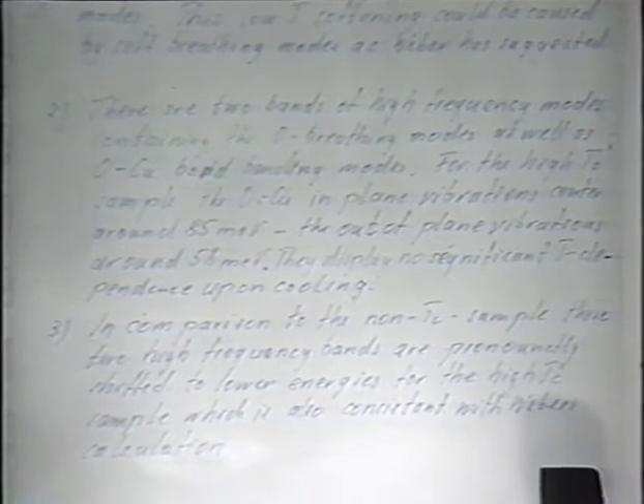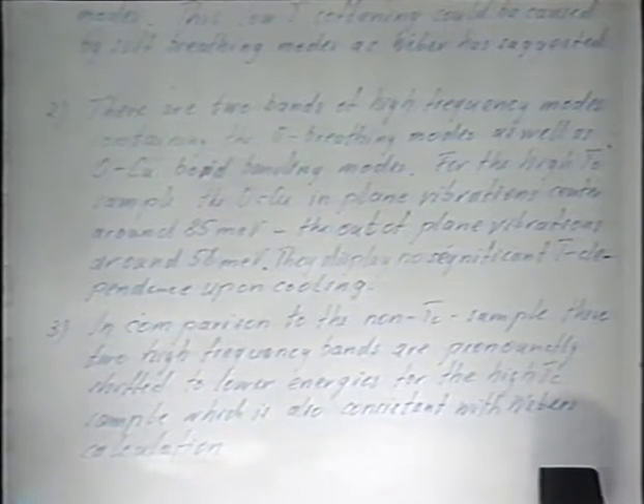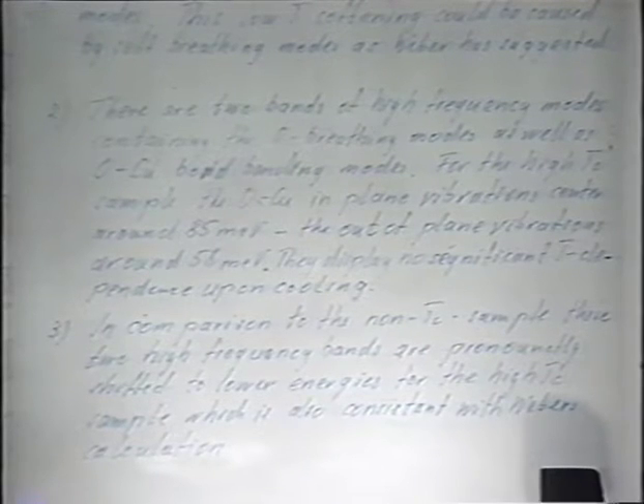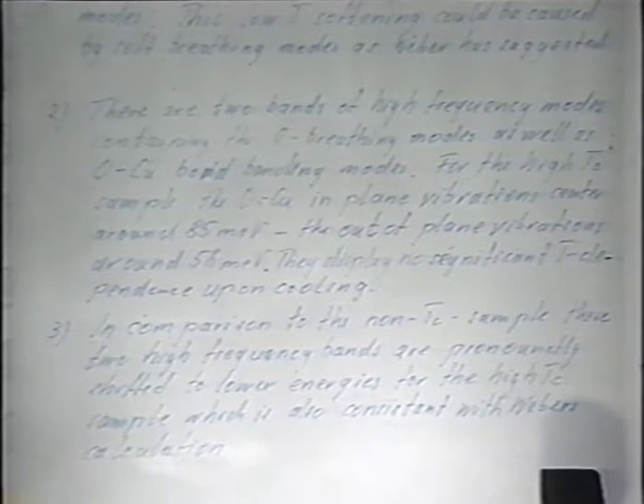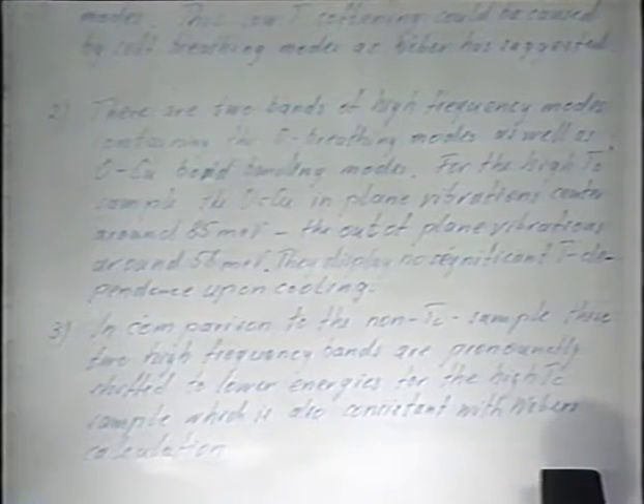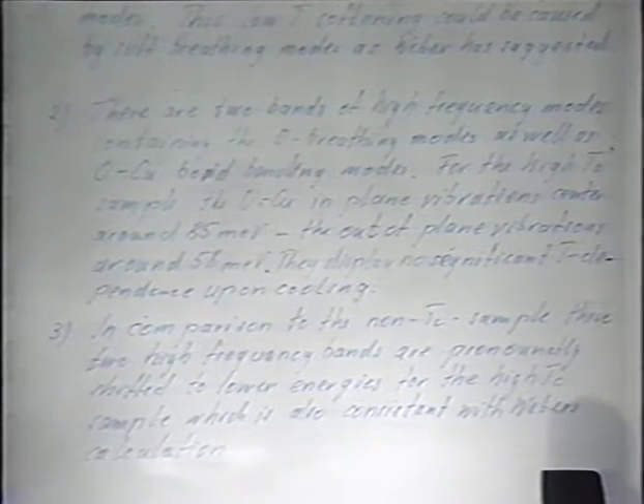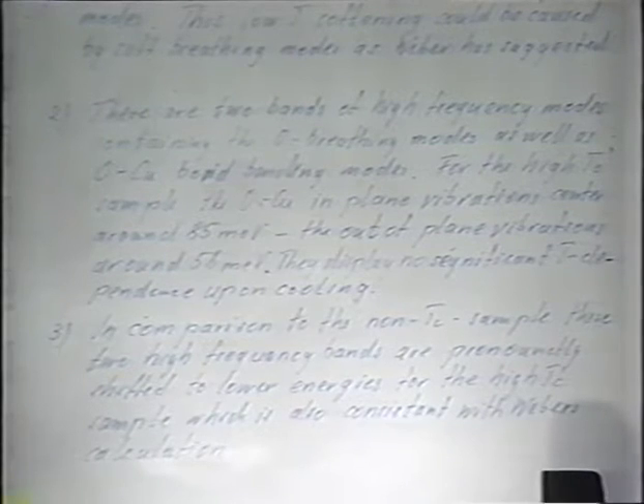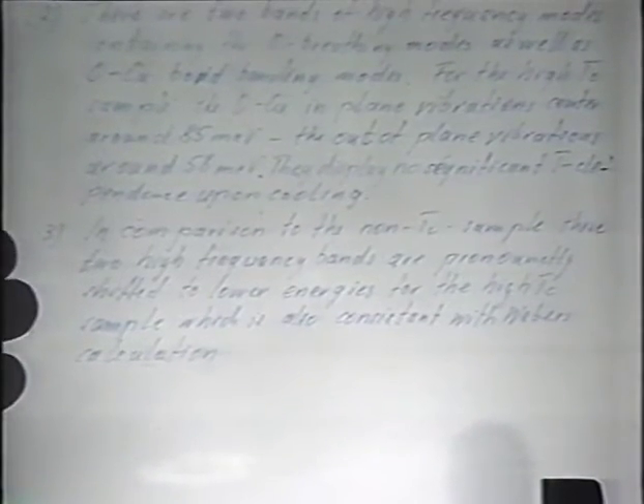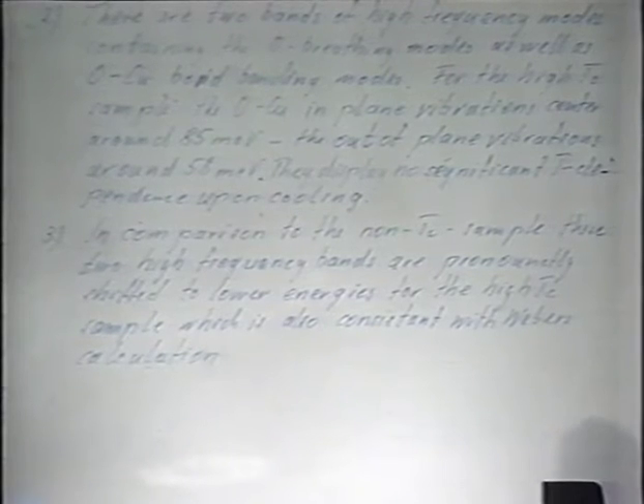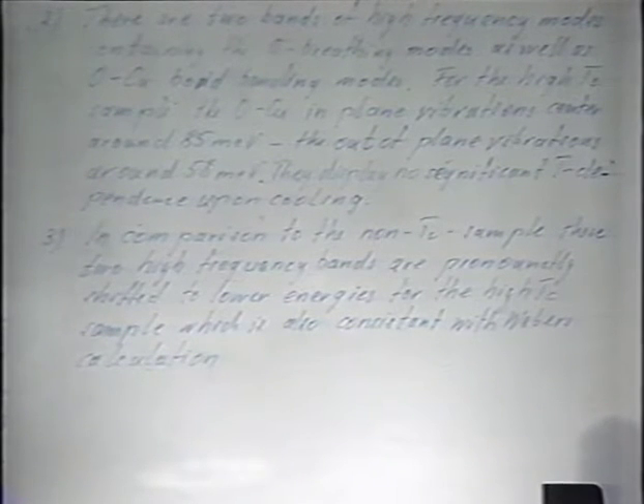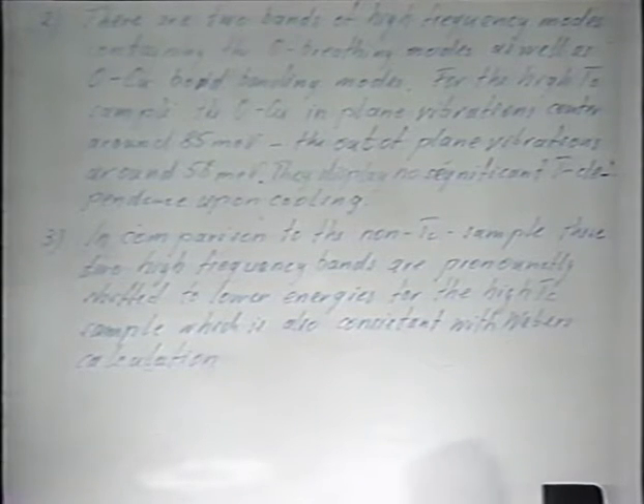Secondly, there are two bands of high-frequency modes containing the O breathing modes as well as Cu-O bond bending modes. For the high TC sample, the Cu-O in-plane vibration is centered around 85 millieV, the out-of-plane vibrations around 58 millieV. They display no significant T dependence upon cooling. In comparison to the non-TC sample, these two high-frequency bands are pronouncedly shifted to lower energies for the high TC sample, which is also consistent with Weber's calculations.